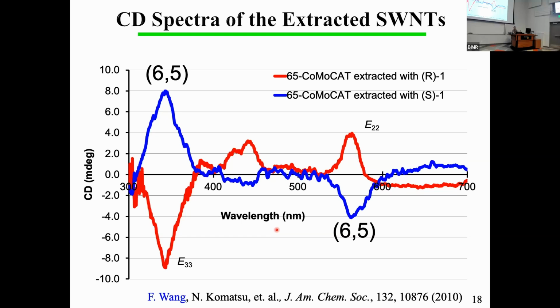This is circular dichroism. As I told you, we independently extracted single-walled carbon nanotubes using the R structure nanotweezers and the S structure nanotweezers, and got two samples dispersed in D2O in the presence of the achiral surfactant SDBS. Then we measured the CD, and we can clearly see symmetrical CD spectra from the R structure host molecule and the S structure host molecule. It clearly shows our extracted carbon nanotube is definitely optically active.